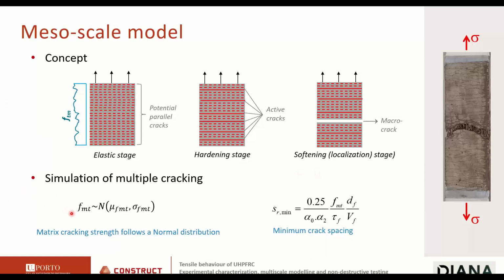How do we simulate multiple cracks? Because the actual stress is constant on the specimen, how do we allow for multiple cracking? As I told you, the tensile strength of the matrix is randomly distributed. We use a normal distribution defined by a mean value and a standard deviation. So all these cracks have different tensile strengths for the matrix component. And then we also define a minimum crack spacing.